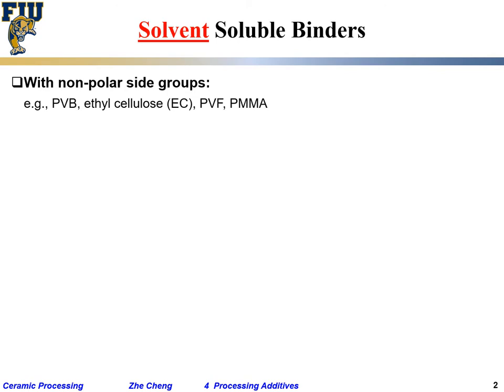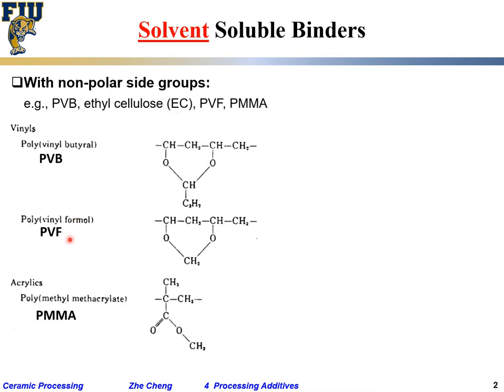On the other hand, there are organic polymers dissoluble in organic solvents. For example, in screen printing, should you use a water-soluble or solvent-soluble binder? Solvent-soluble — because in screen printing, to prevent the paste drying on the screen, you cannot use water; you must use high-boiling-point solvents, quite often terpineol. If you use terpineol, you need solvent-soluble polymers such as PVB (polyvinyl butyral), PVF (polyvinyl formal), or PMMA.